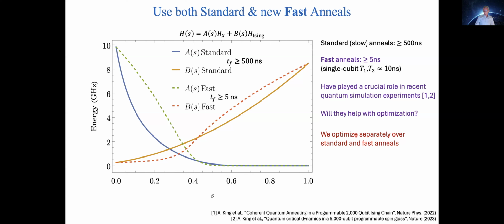So it's great that this worked with quantum simulation, but of course here we're interested to know whether this is also going to help with optimization. And then because the annealing schedules for the fast and the standard anneals are different, we had to separately optimize, that is find the optimal anneal times for these 2 different types of schedules. Okay, so with all that, now I can finally show you the new results.